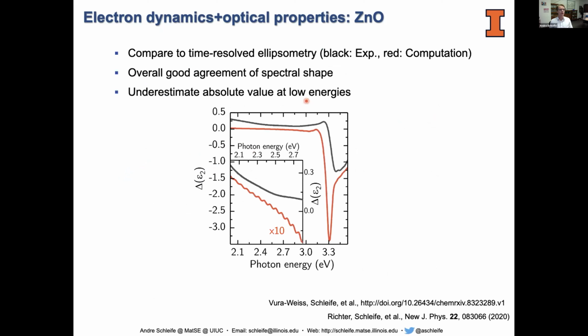Let me just jump to the results in the interest of time, which is a comparison here now between, so that's the delta epsilon, so that's how much the imaginary part of epsilon changes as a function of energy at a certain time, for a certain pump-probe delay. And the black curve is experiment, the red curve is what we computed from our simulation. And you can see that the overall structure of the curve comes out very well in our simulations after we incorporate the effects that I discussed in the previous slide.